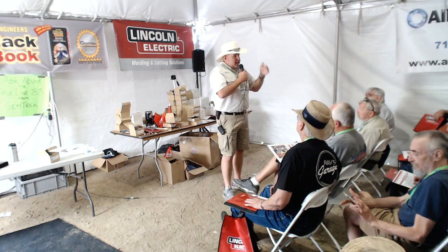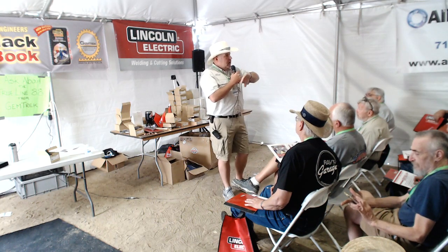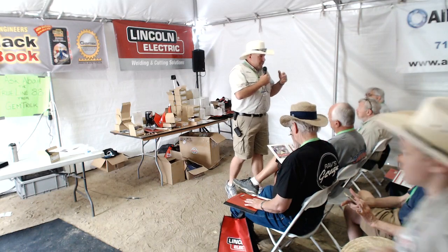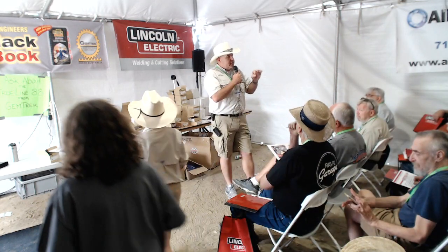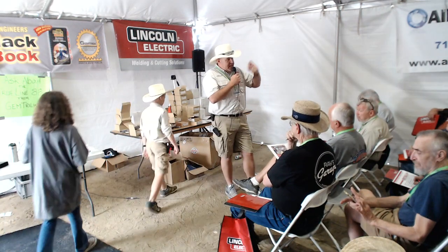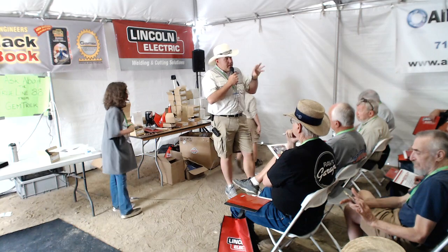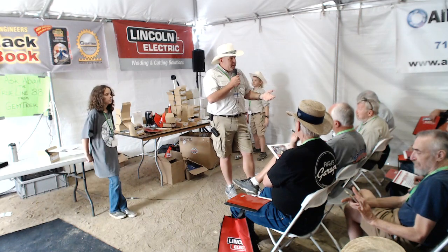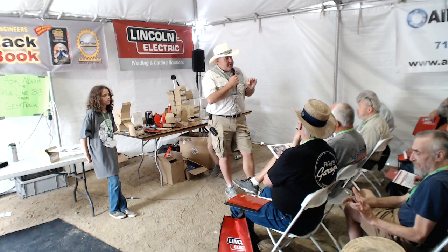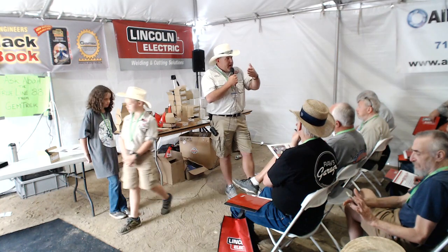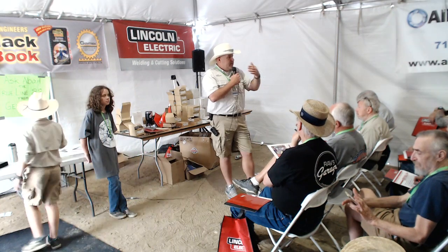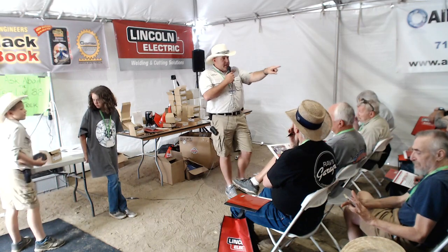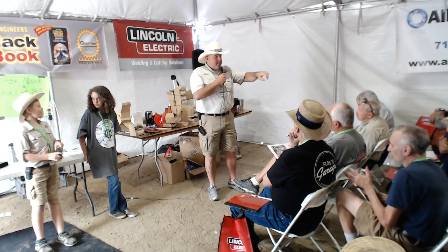Till you get to clean, uncorrupted tungsten. Because once the tungsten is corrupted, anything in that tungsten other than tungsten begins to emit off, and it gets in your weld puddle. That creates what's called a discontinuity, and that's where your crack starts to form under stress. We'll take a minute to talk about that because I didn't cover it.